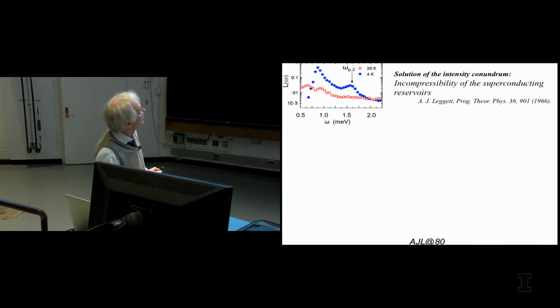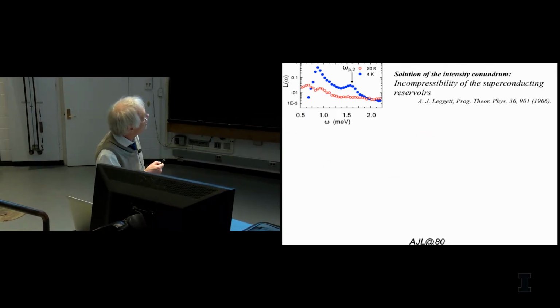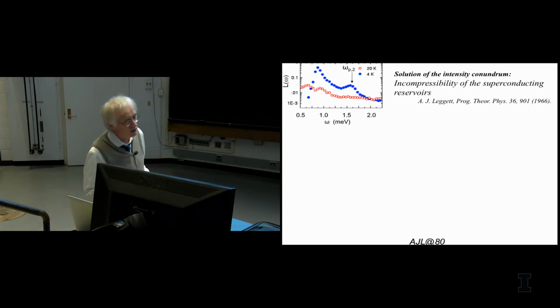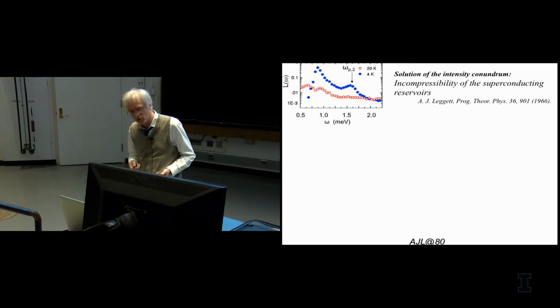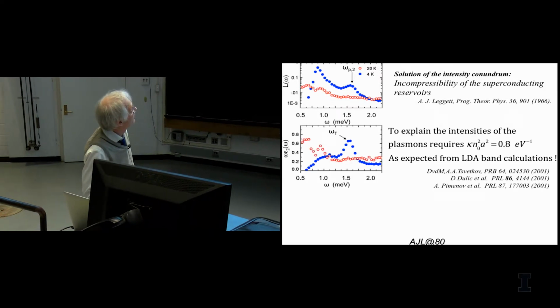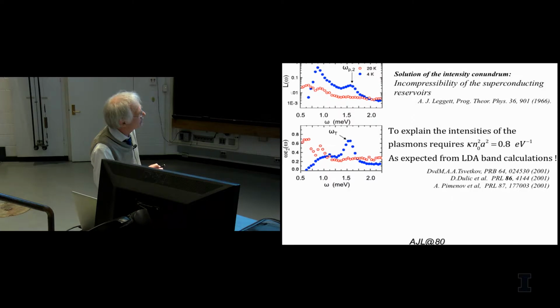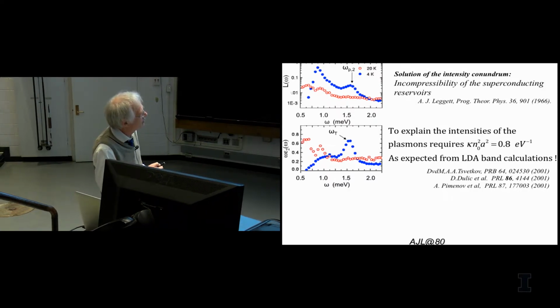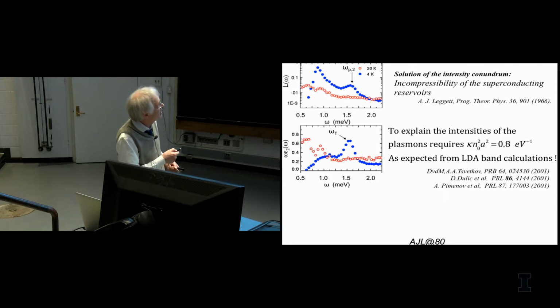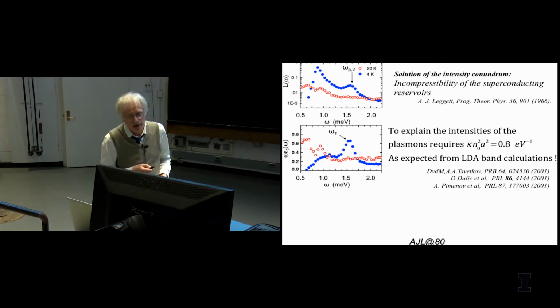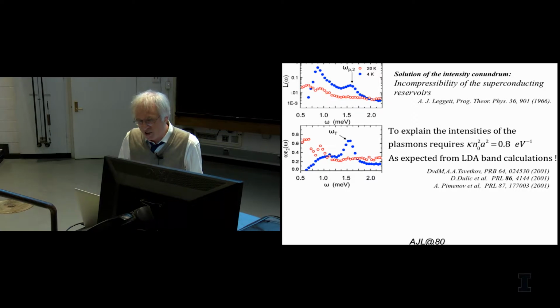Okay, the remedy, the solution of that intensity conundrum, was that you have to take into account the incompressibility, or the finite compressibility, of the superconducting reservoirs, so precisely what Leggett had done. This was actually pointed out to me by Bulaevskii when he was visiting in Groningen at that time. And so, actually, we did it. We derived the same expression, but with a different meaning of the microscopic parameters. You can show that if you put in a density of states of 0.8 electron volt minus 1, corresponding to a compressibility factor related to this density and lattice parameter, then you get precisely this factor of 20 over here. So, indeed, this is the element that was missing, and that was Leggett's story.